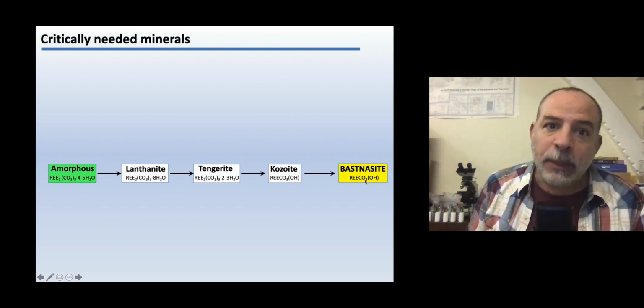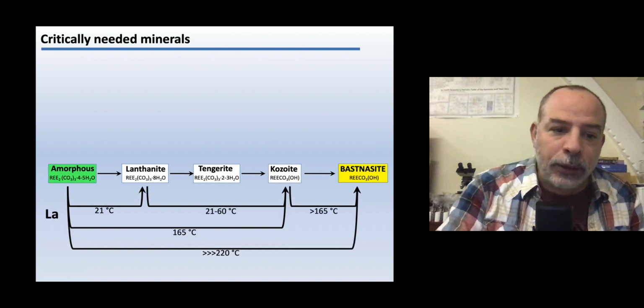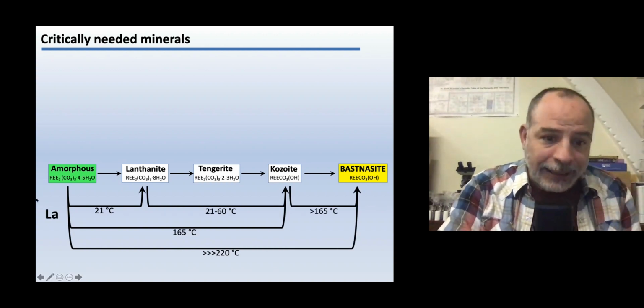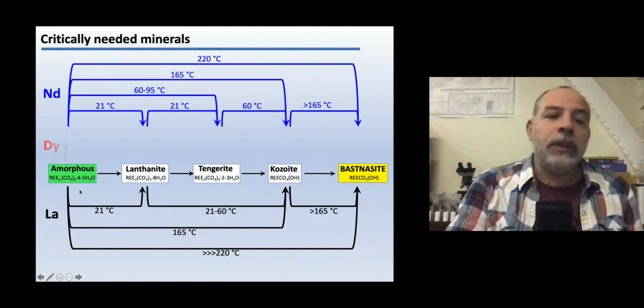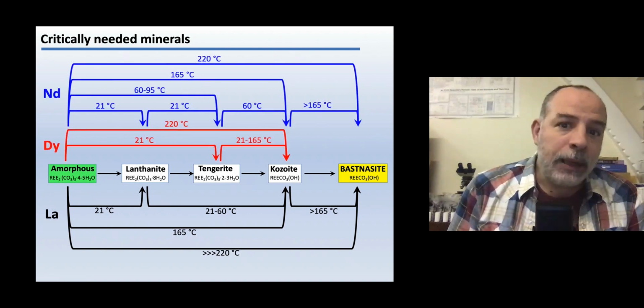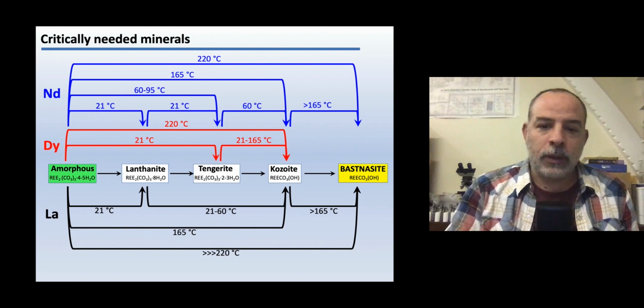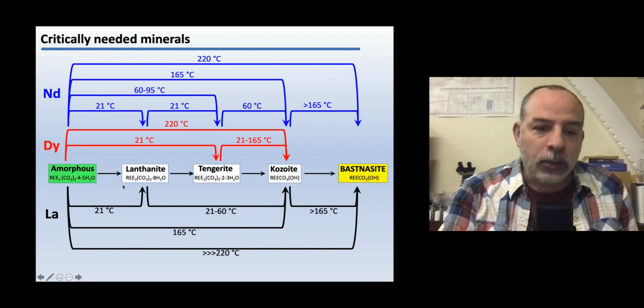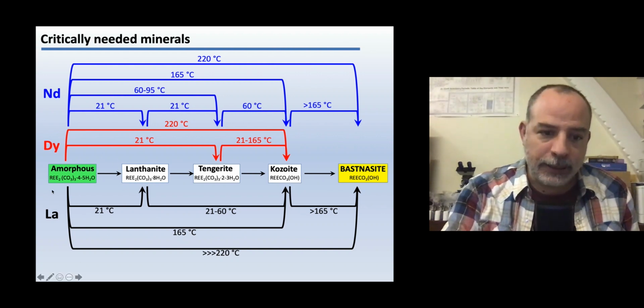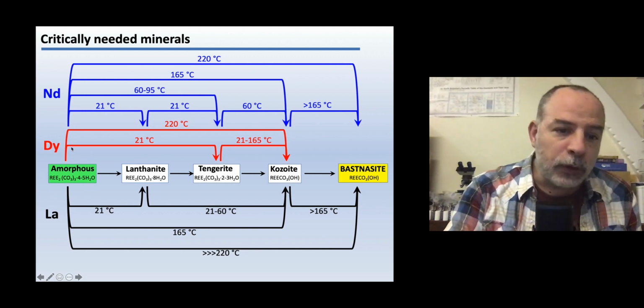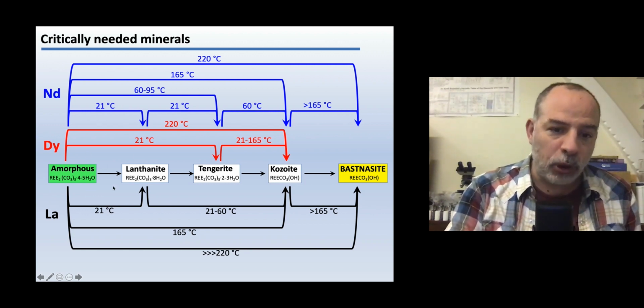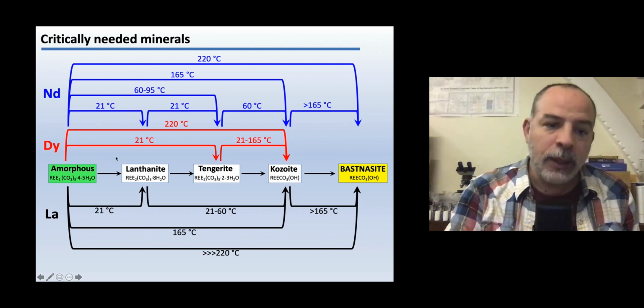This transformation depends on the rare earth element involved. The kinetics and the temperature required depend on the rare earth element, and therefore this is a very complex system to work. Okay. So one thing that we have been trying to understand is what happens at the early stages when we form an amorphous phase and then transforms to the first polymorph, lanthanite, because we want to know if something else is forming here.